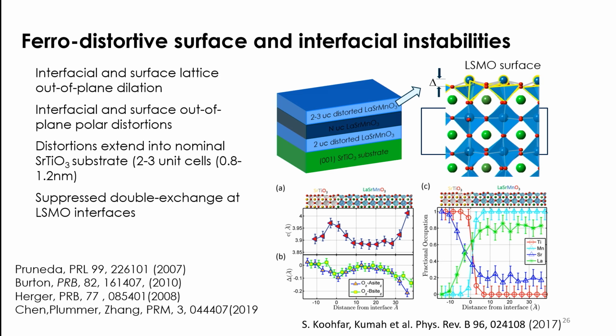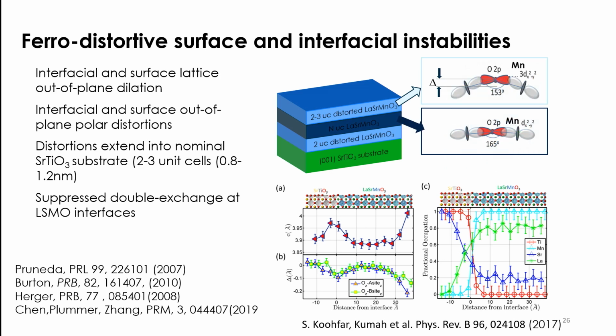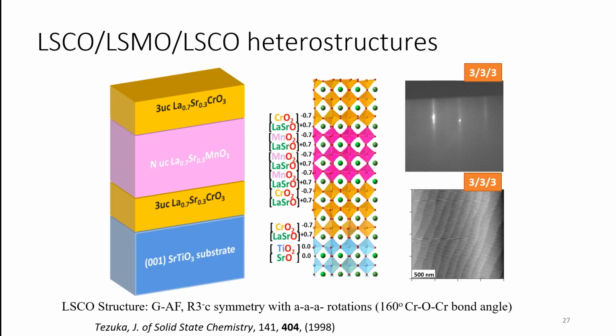But the main reason why these distortions are important, and we find that even if you go to a 4 unit cell thick film, you still have a surface region which is highly distorted, is the magnetic interactions. Again, I told you about the bond angles, right? So if you now have this kind of polar distortion, you're also effectively changing the bond angle between oxygen, manganese, and the neighboring oxygen, and increasing the bond length. And this is what we think is related to why these very thin films lose their electronic and magnetic properties.